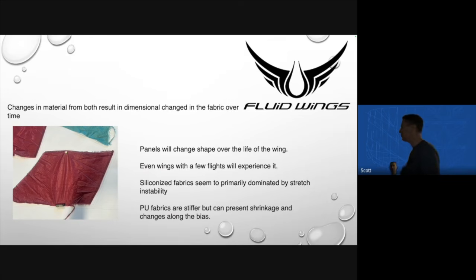That's one of the dangers when you see that. When we replace a cell, we want to do it symmetrically, right? It's because when you sew the same CAD, same exact dimension as the original size, you sew it back on, the wing you're putting it back onto has changed shape over time. Those panels no longer match as cleanly as you would like. And so if you were to do it asymmetrically on the wing, there's a really good chance that part of your wing is not the same shape as the other part of the wing, and you run a chance of not having a symmetrically flying wing.